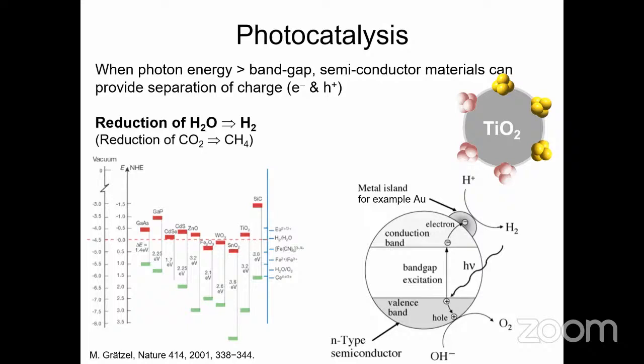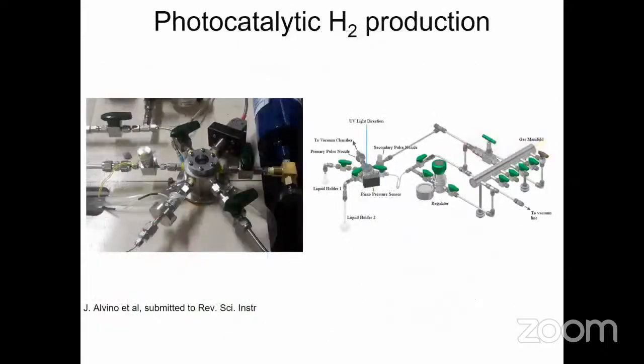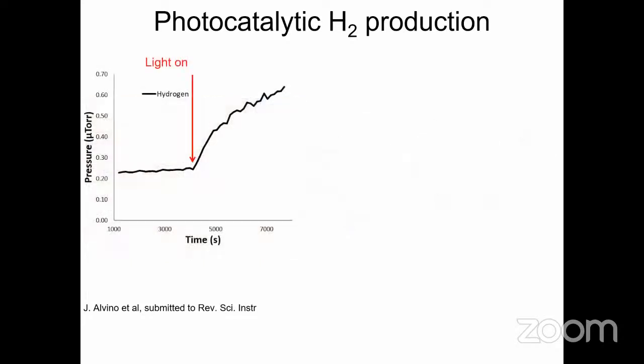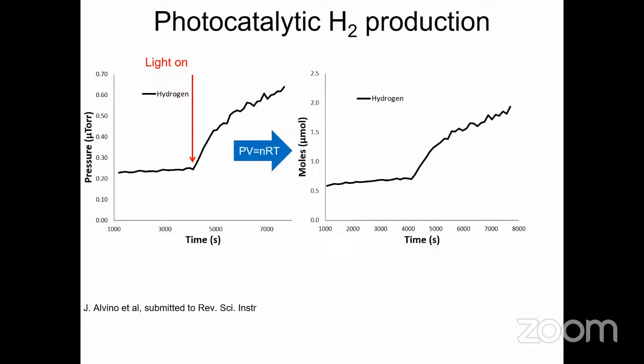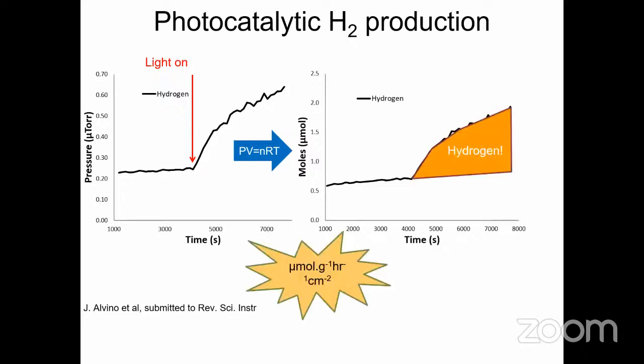And our group in Adelaide Uni, they created a reactor in which we can perform the catalytic reaction itself. And this reaction can measure very precisely a difference in pressure produced by the hydrogen itself and can measure a very small amount of the hydrogen production, reaching to the micromoles.